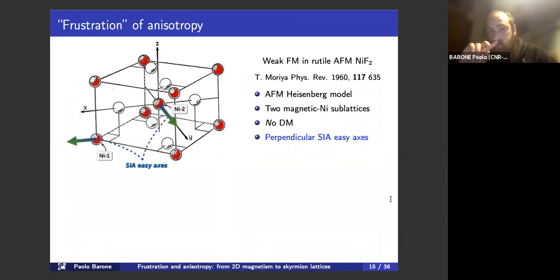Now we can also have another class of frustration, which is not related to the competition between exchange interactions. This also has been proposed by Moriya a couple of months before the publication of his famous paper on the Dzyaloshinskii-Moriya interaction. And he proposed this mechanism trying to explain the weak ferromagnetism, so a non-collinear phase in an antiferromagnet, which is nickel difluoride. And so in this system, the structure is relatively simple, as shown here. The main ingredients are the fact that the interactions are mostly isotropic antiferromagnetic. There is no Dzyaloshinskii-Moriya interaction.